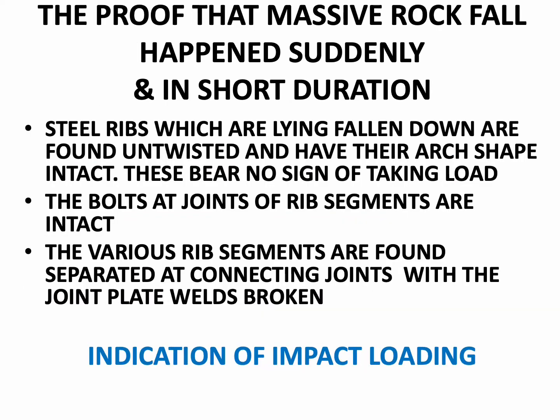The proof that the massive rockfall happened suddenly and in short duration lies in this, that the steel ribs which are lying fallen down are found untwisted and have their arch shape intact. These bear no sign of taking load. The bolts at the joints of the rib segments are intact. The various rib segments are found separated at connecting joints with the joint plate welds broken. These all indicate the happening of an impact loading.